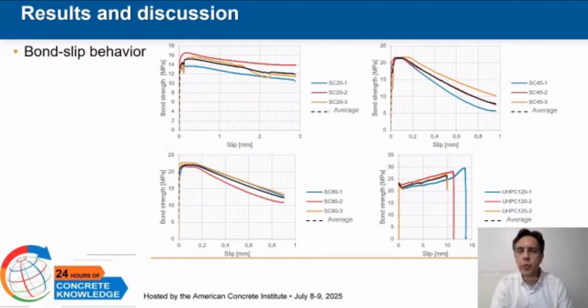The UHPC 120 curve is different. It shows a steep linear rise and a sharp drop after the peak, which is typical of brittle debonding. Its extremely dense matrix provides strong mechanical interlock but minimal energy dissipation once slippage begins. These curves confirm that bond performance depends heavily on concrete compressive strength and matrix structure, and that UHPC presents unique design considerations due to its brittle failure mode. These findings are critical for defining development lengths and anchoring strategies for GFRP reinforced elements in high-performance concrete.